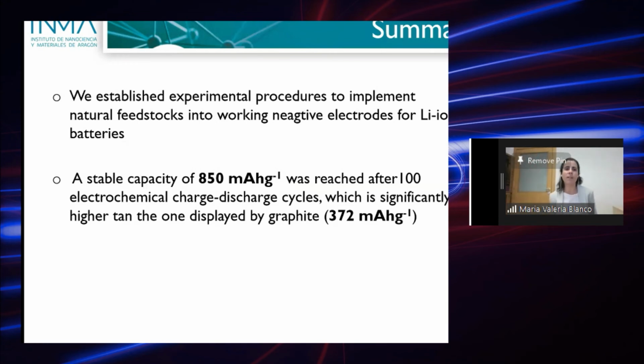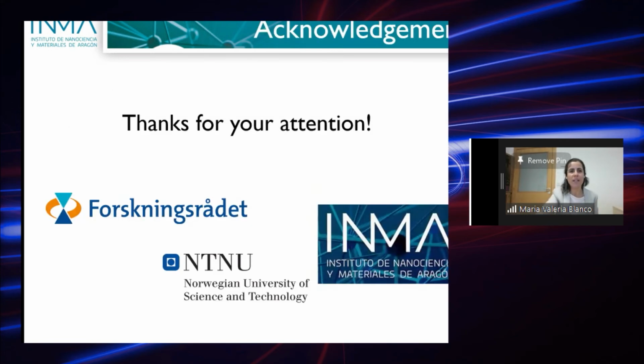So as a summary, I can say that we established an experimental procedure to implement this natural feedstock into working negative electrodes for lithium-ion batteries, and we were able to reach a storage capacity of 850 milliamp hours per gram after 100 cycles, which is much higher than the one displayed by graphite, that is about 372 milliamp hours per gram. So this is where we are now.